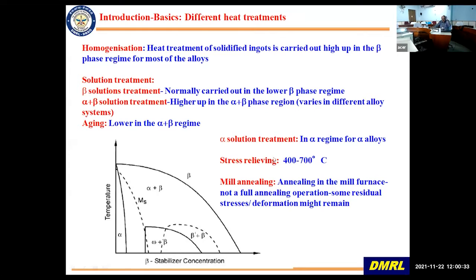Then most of the time, the stress relieving of titanium alloys is carried out in the temperature regime of 400 to 700 degree centigrade. And there is also a term called mill annealing. Now, what is mill annealing? Mill annealing is annealing in the mill furnace. That is the furnace that you are using for deformation, for wrought processing of the alloy. You give some annealing operation, let's say after deformation, for roughly 1 hour or so, not much. So some residual stresses and deformation might remain after mill annealing. And this is a standard term which you will see in many supplying companies and all. So that is why I'm trying to introduce you all to it.